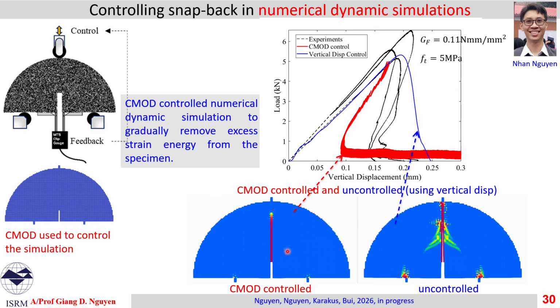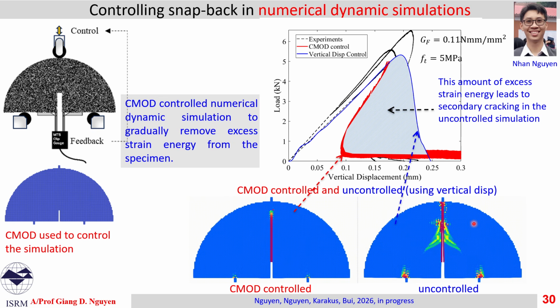Yes, and the failure patterns look very different. There is a very clean crack in the well-controlled one, while in the uncontrollable one, fracture happens very fast. The difference between the two simulations is this area, which is the energy used to create more secondary cracking in the uncontrolled one.